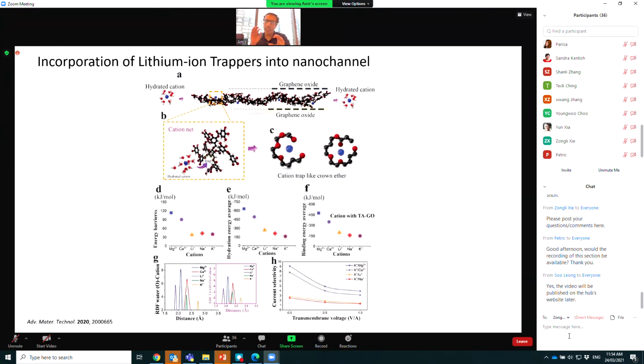In that project, our initial idea was to incorporate ion trappers inside the nanochannel, and also to manipulate the space through which ions can transport. So we have two elements to play around with, and using those parameters, we managed to alter the binding energies, hydration energy, and barrier energy to allow other ions to transport through the nanochannel while holding lithium.